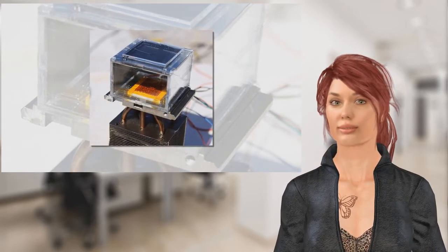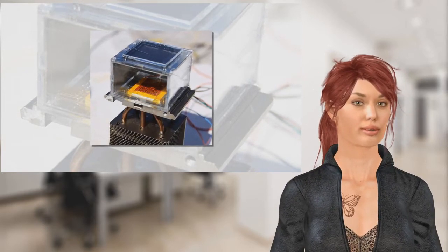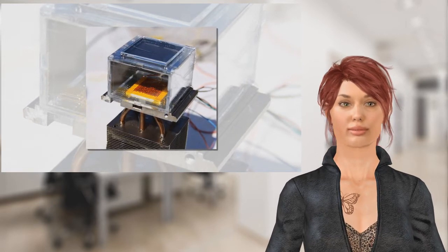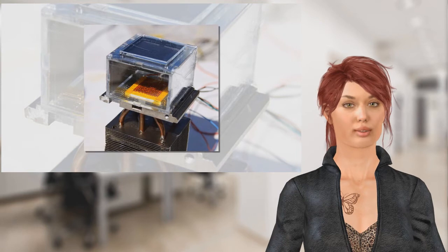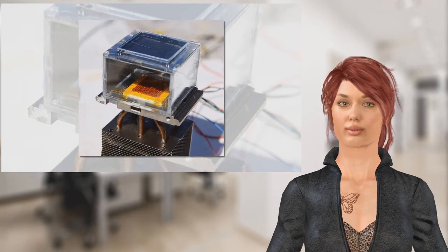Your electric dehumidifier at home produces very expensive water. The prototype, under conditions of 20 to 30 percent humidity, was able to pull 2.8 liters, or nearly 5 pints, from the air over a 12-hour period using 1 kilo or 2.2 pounds of MOF.